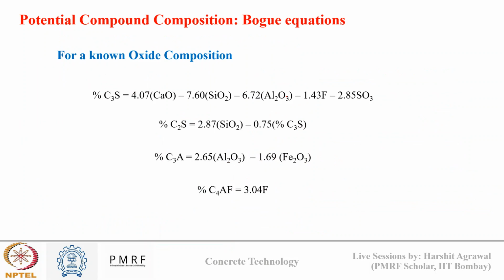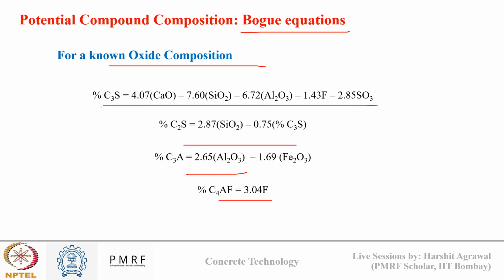Now before passing any material through the kiln phase, suppose we know the oxide composition of a raw meal. How will we proportion the raw meal to get the final compound composition that we want? For that we have an equation known as Bogue's equation. If we know the oxide composition of cement, using these four equations we can determine the final compound composition in cement. Based on this we can make minor adjustments in the raw materials we are mixing, so that we can adjust the final products. So Bogue's equation relates the oxide composition to the compound composition.